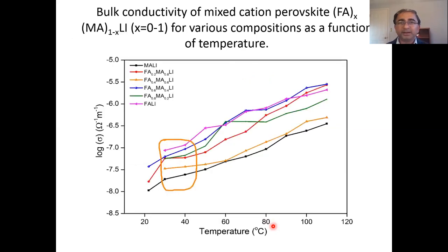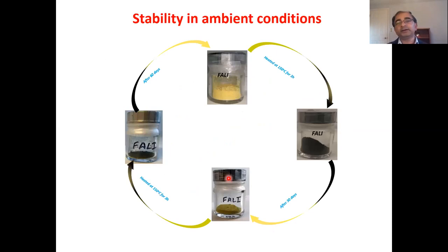I have done some conductivity measurements using impedance spectroscopy, and you can see it here. It is very interesting to see that this is a yellow phase which I am getting, and if I heat this yellow phase at 150 degrees for a particular time, I get a black perovskite phase, and this is used in solar cells.